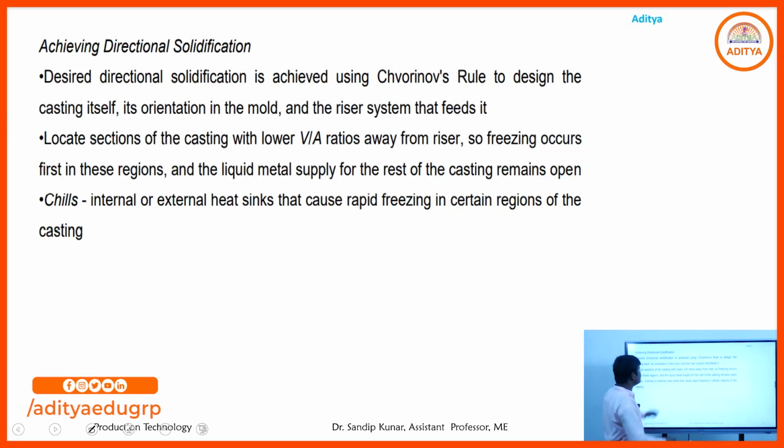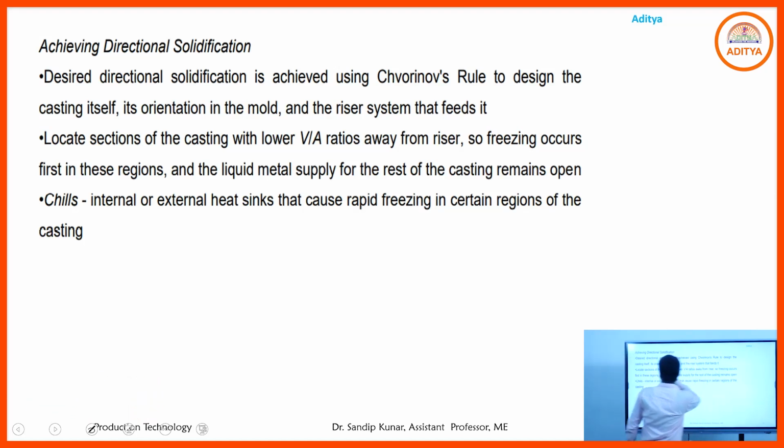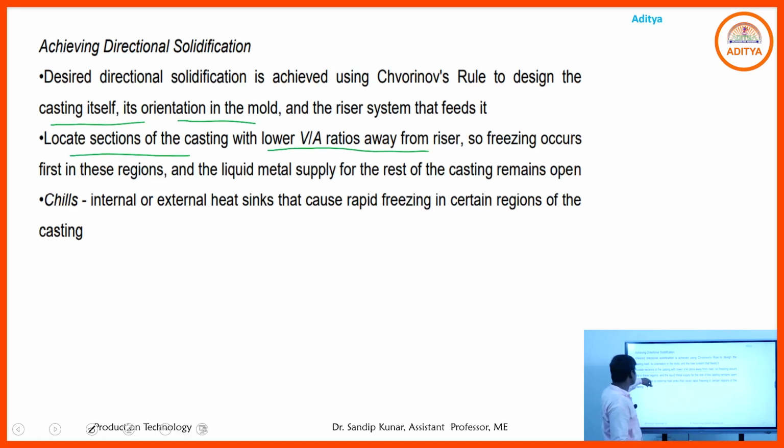Achieving directional solidification: what happens in that case? We have seen that as per Chvorinov's rules, we design the casting itself, its orientation in the mold, and the riser system that feeds the molten metal to the mold cavity. Locate sections of the casting with a lower volume ratio away from the riser, so freezing occurs first in these regions. The liquid metal supply for the rest of the casting remains open. Solidification starts at the surface across the mold surface, where more heat extraction takes place, then it goes towards the center.